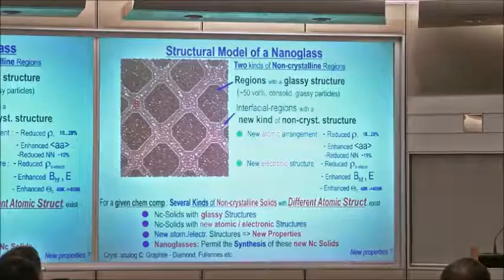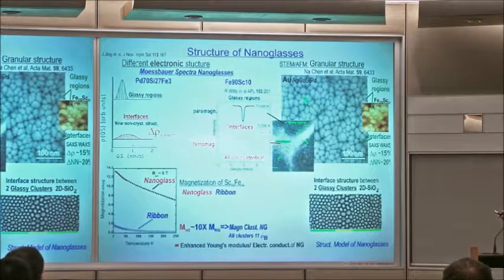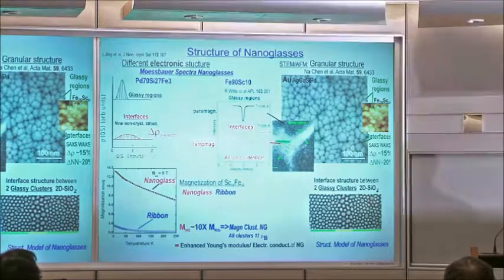Yeah, what I can show you perhaps what we can see. Big glasses and small glasses, apparently what is important is that the free volume which is caught in the interface gets smeared out so that the nanoglass can form this layer. Here you can see a little bit. These particles have a size of about 5 to 6 nanometers, and here is the interface. It's a uniform thickness, about 2 nanometers in size.